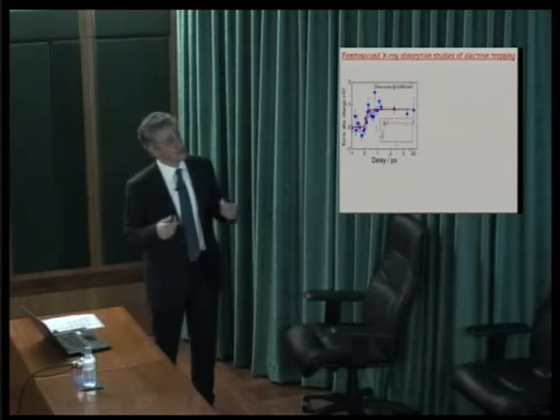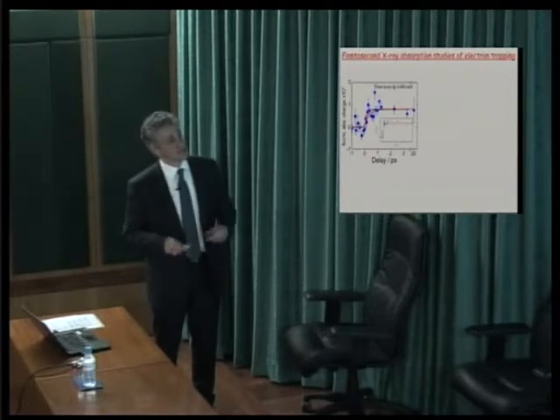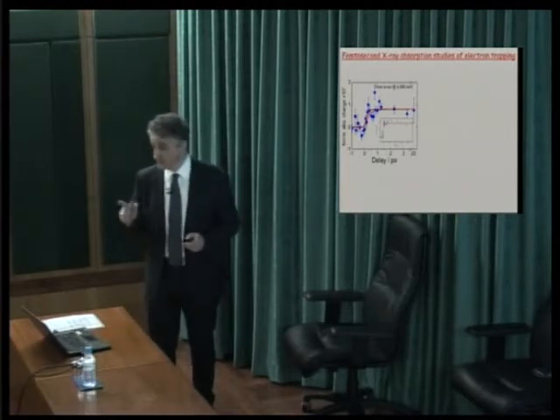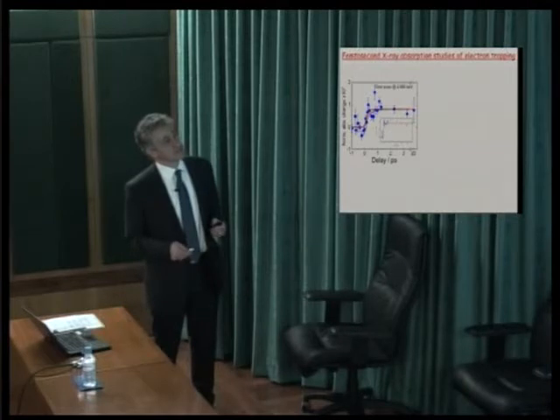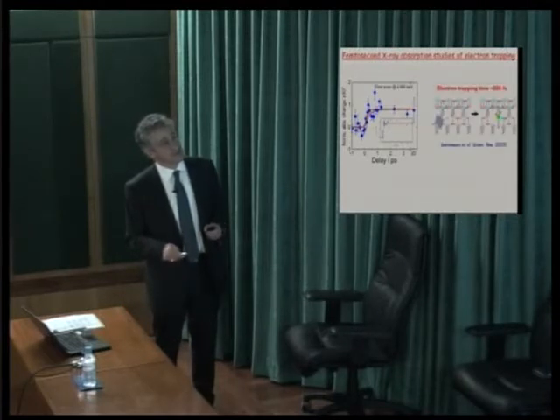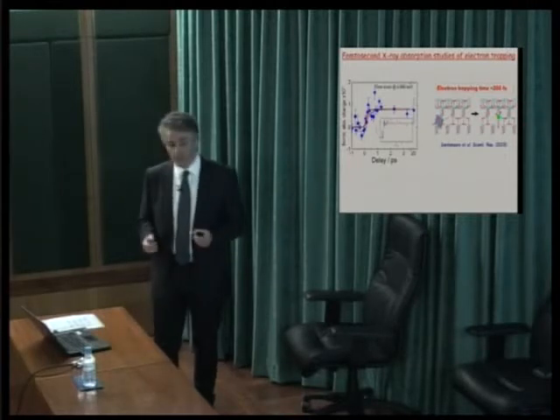We looked at the trapping time of the electron in these defects. You see the error bars are large because the count rate is extremely low. It took us a week to record this, just a week. And then what this says basically is that in less than 200 femtoseconds, you have the electron that gets trapped at these pentacoordinated defects, where the blue dots are the titanium and the red ones are the oxygen.